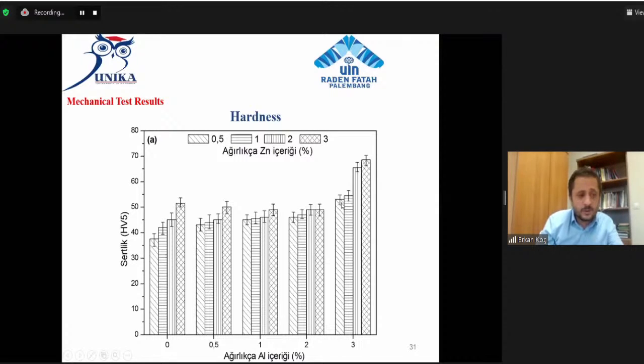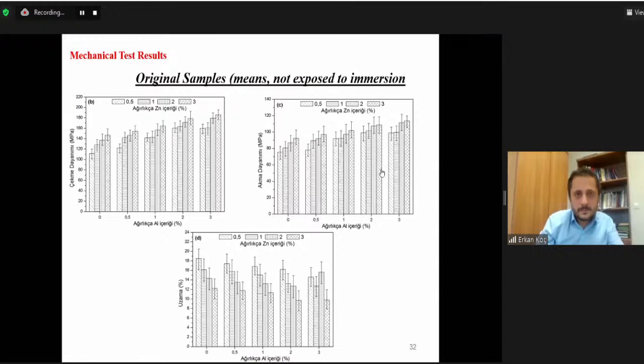When the amount of aluminum reaches 3%, a remarkable increase in hardness is observed because of, as I said here, the intermetallic phases. Intermetallic phases affect hardness. As seen here, and tensile strength, yield strength, and elongation.